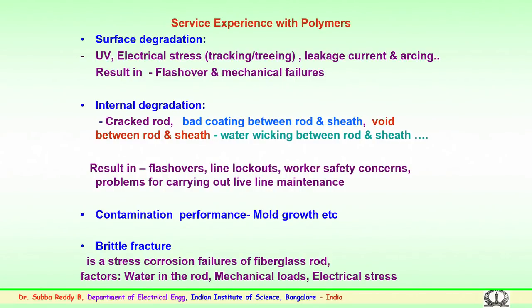In case of damage to the surface of the insulator, water, moisture or fog enters this junction. Over a period of time, because of the continuous corona, there could be formation of nitric acid. This nitric acid interacting with the rod could stress it both mechanically and electrically, and failures have been reported as brittleness, or brittle fracture as it is known. So, this has to be properly taken care of, and maintenance has to look into ensuring the insulation on the surface of the fiberglass rod does not get eroded.